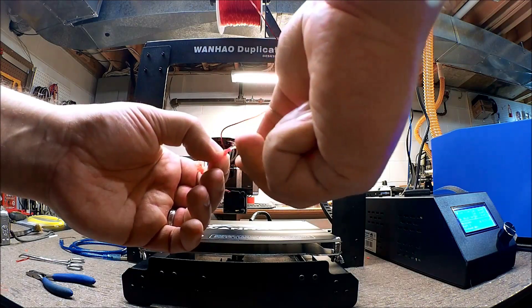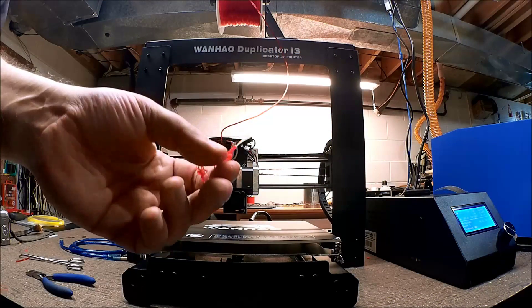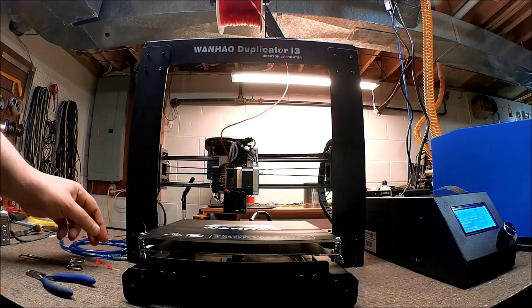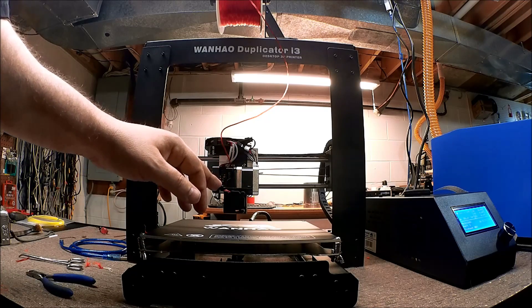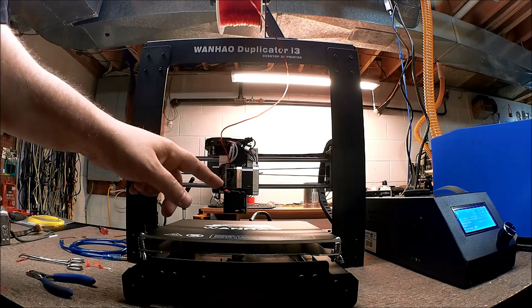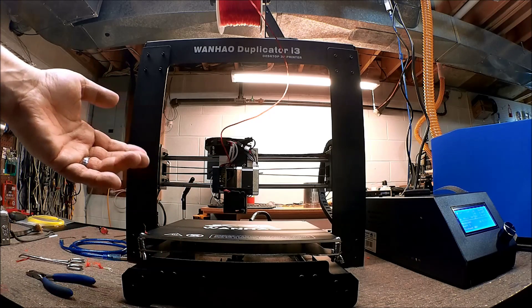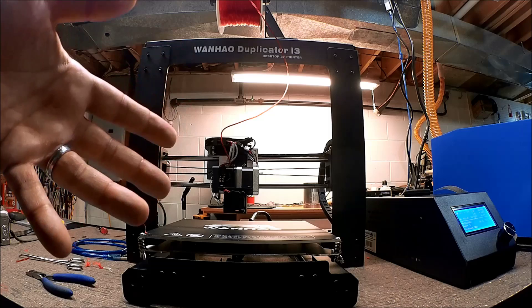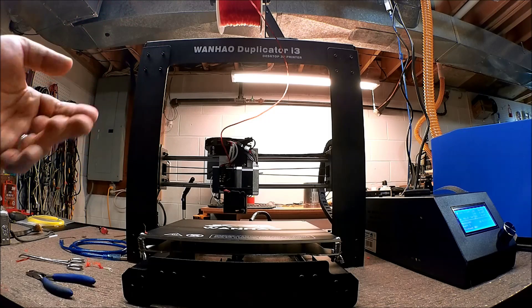It is rather hard when it's solid, but it's kind of interesting. We're going to go ahead and print it. I'm going to be printing at 250°C on the nozzle, 80°C on the bed, and we're going to see how it goes. I'm going to be doing a print that I've done before — we'll cut to a time lapse.